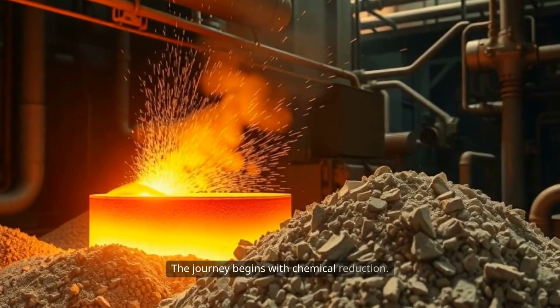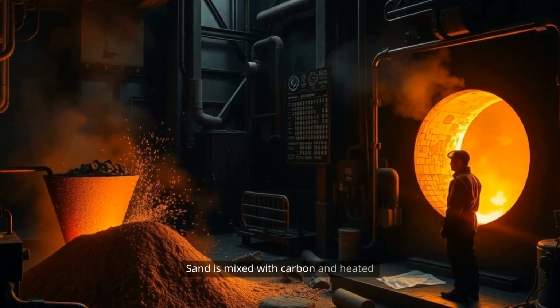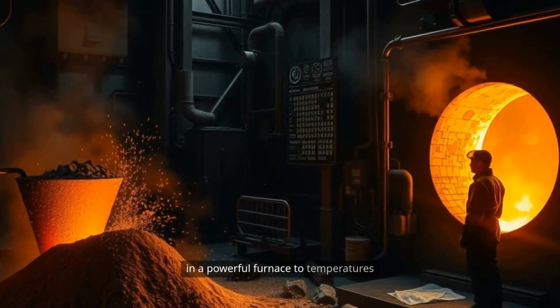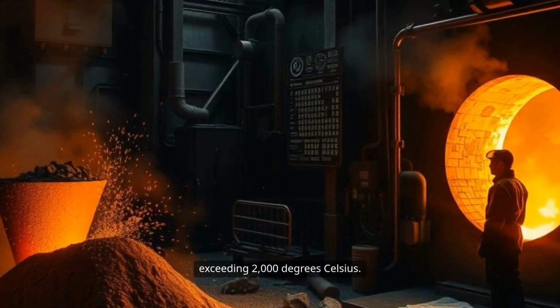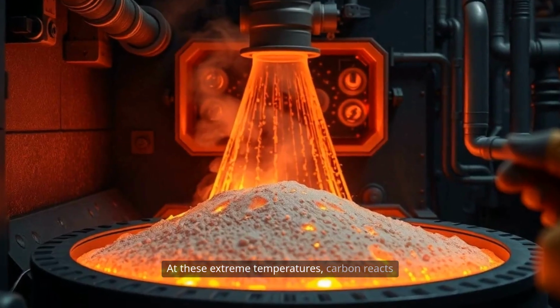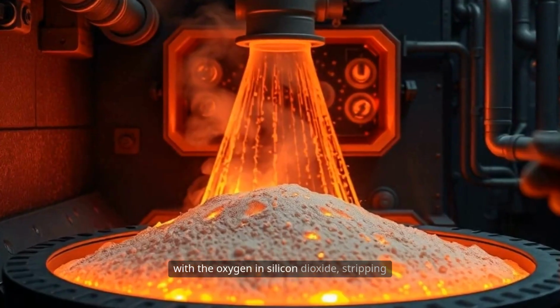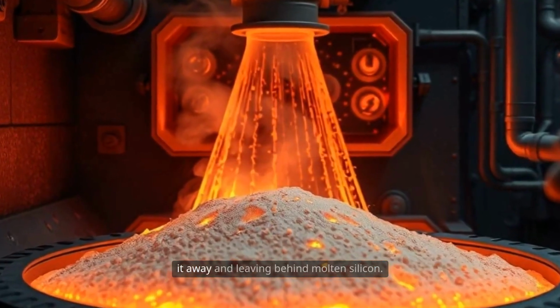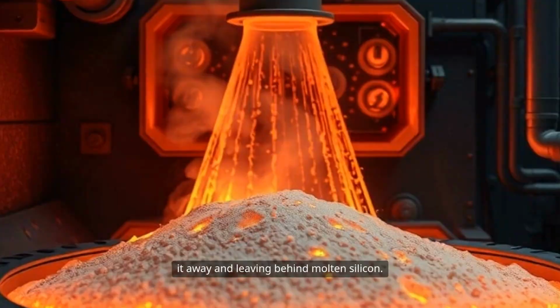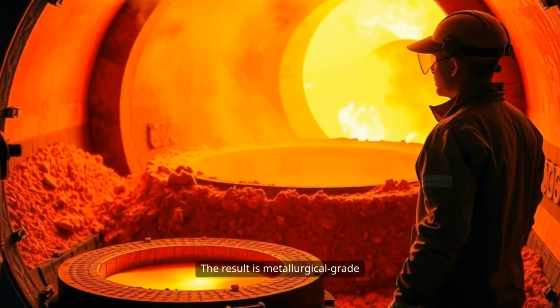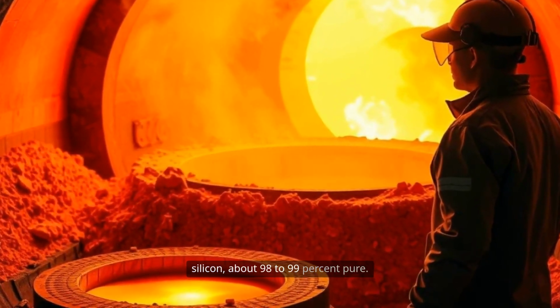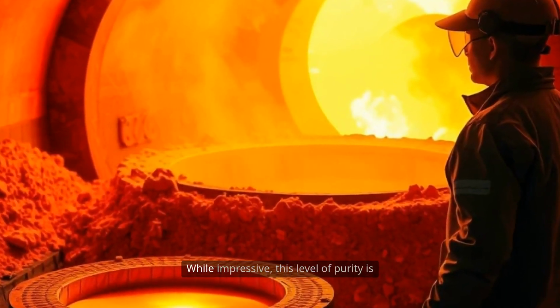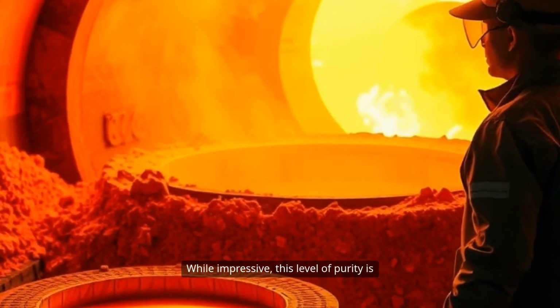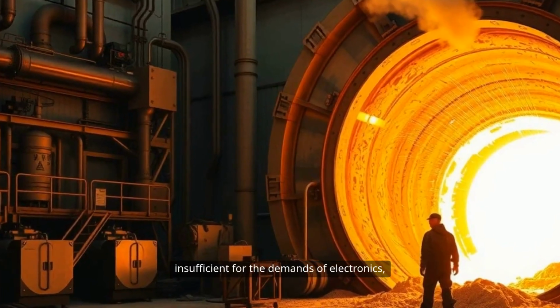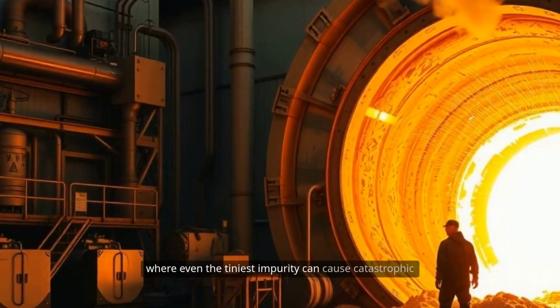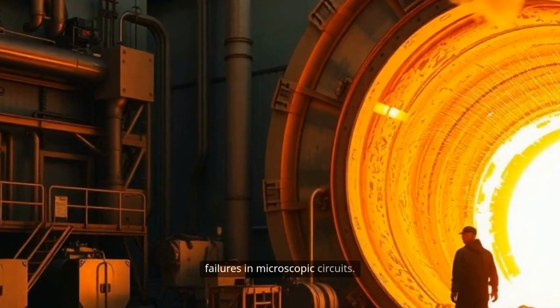The journey begins with chemical reduction. Sand is mixed with carbon and heated in a powerful furnace to temperatures exceeding 2,000 degrees Celsius. At these extreme temperatures, carbon reacts with the oxygen in silicon dioxide, stripping it away and leaving behind molten silicon. The result is metallurgical grade silicon, about 98 to 99% pure. While impressive, this level of purity is insufficient for the demands of electronics, where even the tiniest impurity can cause catastrophic failures in microscopic circuits.